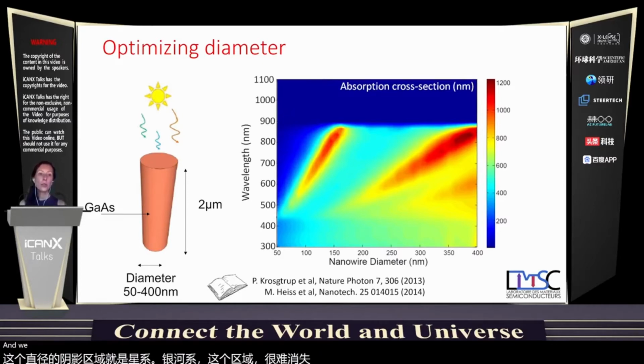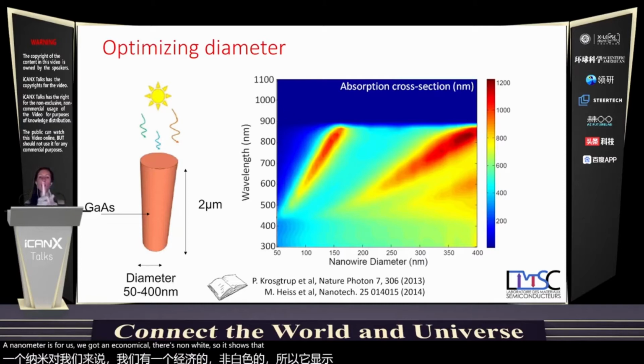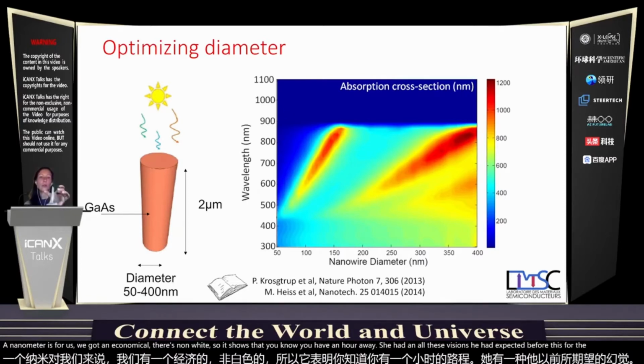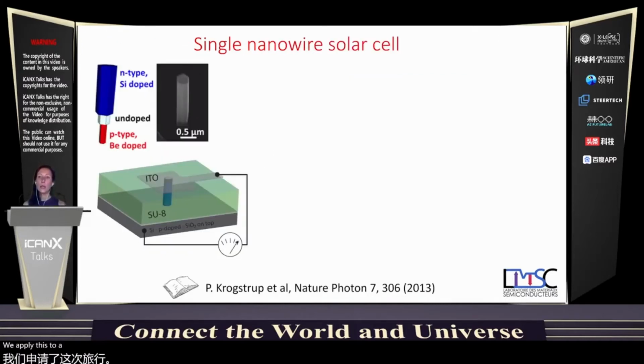And we see that for the ideal diameters, it can go up to 3 times the diameter, so 1200 nanometers for a 380 nanometer nanowire. So it shows that you have a nanowire here, and all these regions here act actively for the nanowire to absorb the light. We applied this to a single nanowire solar cell.